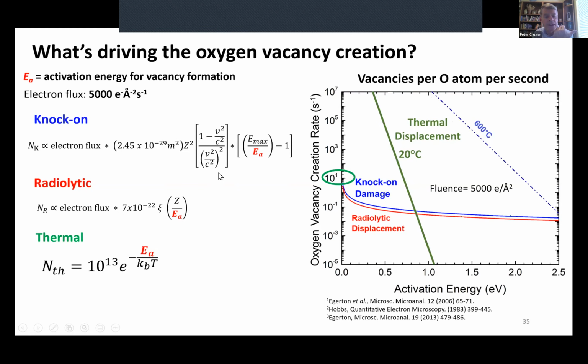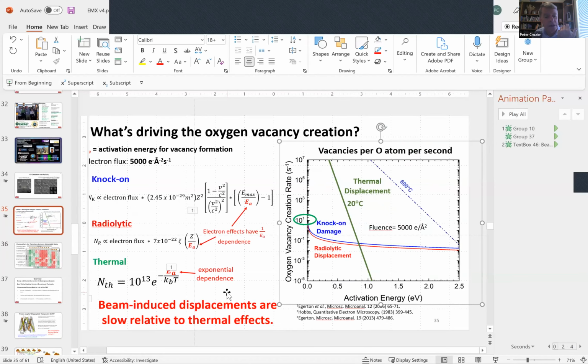So I think that for a lot of the in situ experiments that we're doing, we have to pay attention to electron beam effects, but we also have to remember that many of the thermal processes we're looking at follow this Arrhenius relationship, and that Arrhenius relationship has an exponential dependence on temperature. And so very often, even though we might have some residual radiation effects, when you start to heat the sample up, a lot of the dynamics that we observe is dominated by thermal effects.